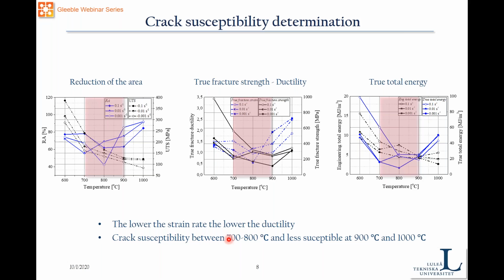And then the crack susceptibility can be said to be between 700 and 800 degrees, and less susceptible at 900 and 1000 degrees. What is happening here normally is that this is mainly related with the recrystallization of the steel.